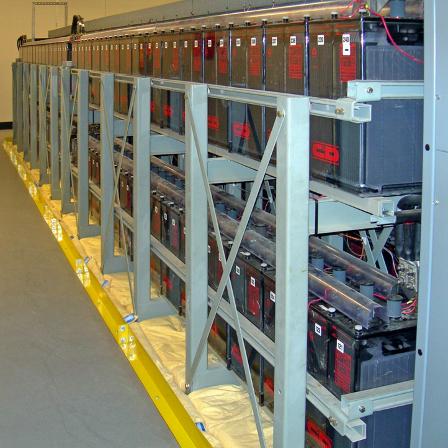A smart battery has voltage monitoring circuitry built inside. Cell reversal can occur to a weakly charged cell even before it is fully discharged. If the battery drain current is high enough, the cell's internal resistance can create a resistive voltage drop that is greater than the cell's forward EMF. This results in the reversal of the cell's polarity while the current is flowing. The higher the required discharge rate of a battery, the better matched the cells should be, both in the type of cell and state of charge, in order to reduce the chances of cell reversal.